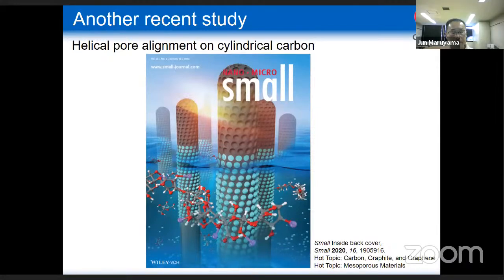And this technique can be applied to make other porous materials that have helical alignment of pores like this. And this helicity can make optical activity. Helicity can impart optical activity to the carbon material itself. And I'm now trying to make use of these special properties for some application. I'm searching the application field right now.